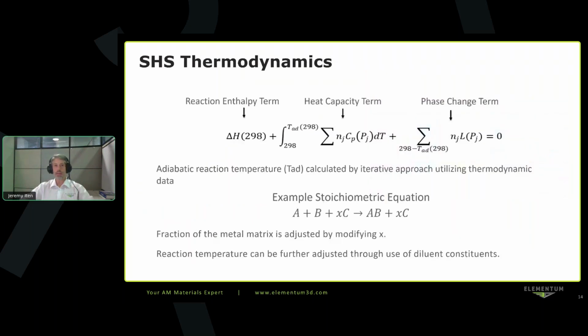So self-propagating high temperature synthesis thermodynamics are based on enthalpy terms. So you've got the reaction enthalpy, you've got the heat capacity of the product material and the reactant material, and you've got the phase change term. So if you're melting the material, if you're changing your crystal structure, there's enthalpy associated with those. And if you do an enthalpy balance, you can now calculate your adiabatic combustion temperature. So the energy released through heat capacity will produce a temperature in your product material, and that's the energy and temperature gain you gain from the reaction.